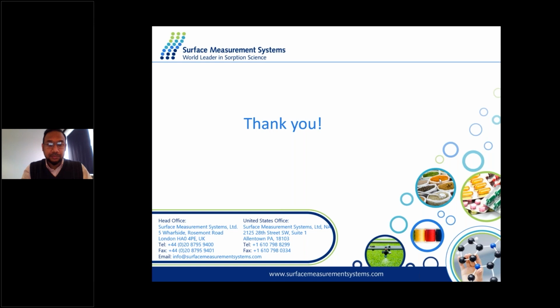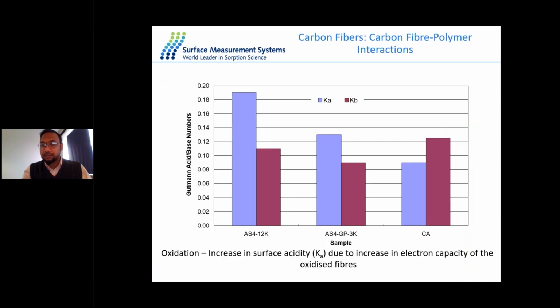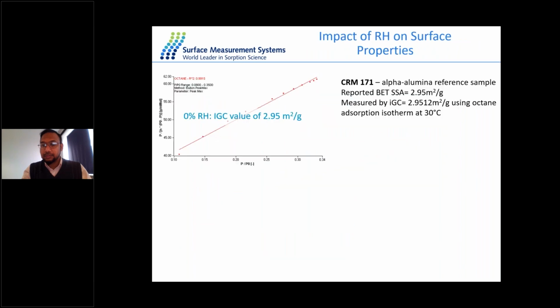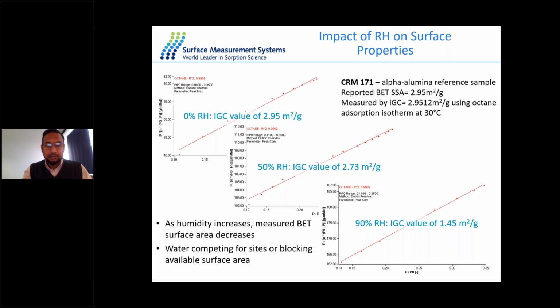So with regards to surface area, if the water is interacting with only the surface of your material, it will be the case of what we've shown in our presentation. Just go back, yeah, so here. Effectively, when you increase relative humidity, you're increasing the amount of water on the surface of your material. And in this case, the probe molecule we're using to calculate BET, in this case octane, would be competing with the water molecules. So we see a gradual decrease in surface area. However, if your material swells when you add water, then this can actually change the BET surface area. If the water molecules go into the bulk of the material and cause a bit of swelling, then we would actually see the reverse. We'll see an increase of BET surface area of your material.